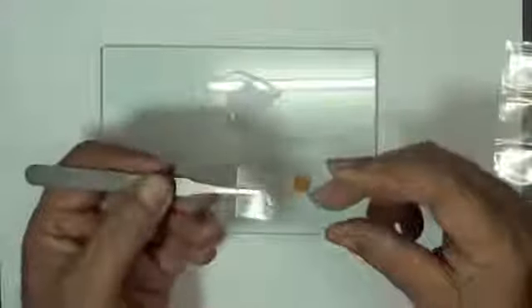You know, when you lay the strain gauge out, it's important that you lay it out shiny side up. VJ will illustrate that, but the surface of the strain gauge on the bonding side has been treated, and it has a dull matte surface finish. That's the side that's going to be down on the glass and later down on the aluminum surface. So we're going to lay this gauge out shiny side up.